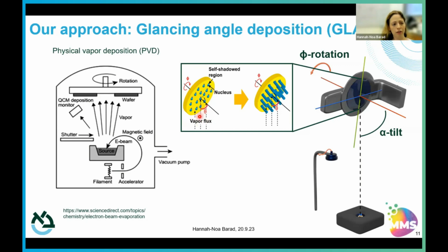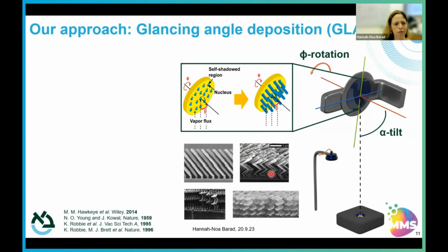And these seeding areas that form are actually the little self-shadowed regions that then interfere and kind of block the vapor flux gradient from coming in. So any of these seeding layers are pretty much where your material will be deposited, and nothing will be deposited behind them. And that is essentially what controls the formation of these different nanostructures during glancing angle deposition. So you can really form quite a wide variation of different types of structures, as I showed you already before, but they can go from nano size till micron size, which is very significant, I have to say.